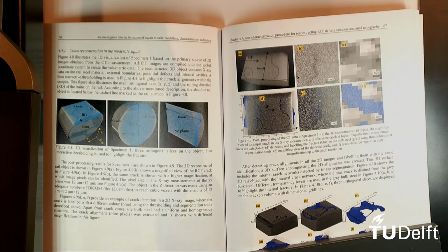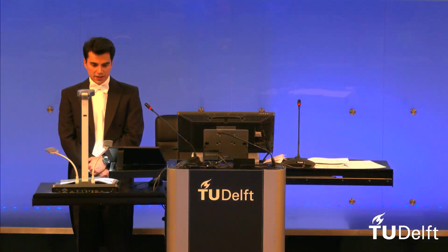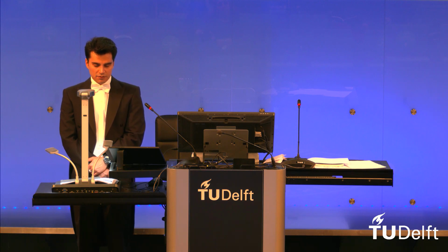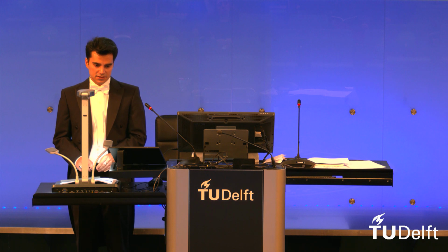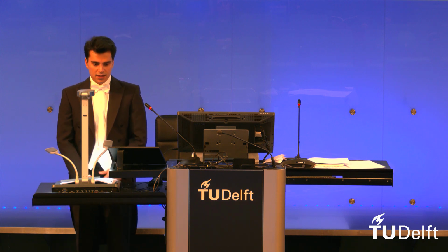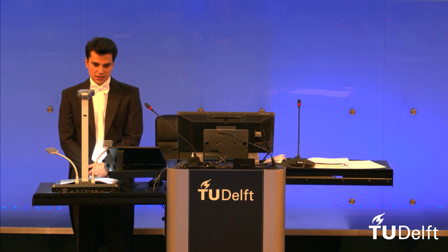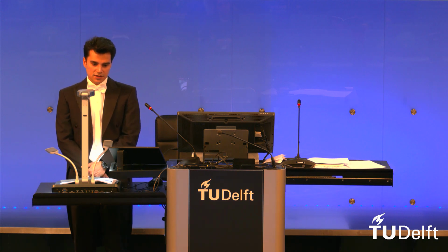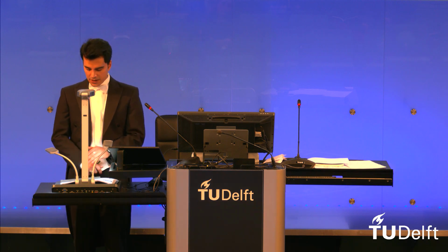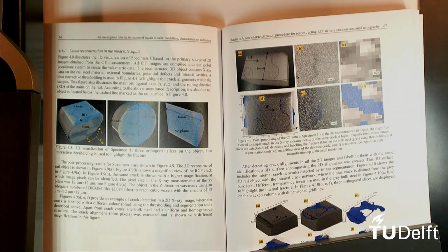And of course, there are also a couple of techniques in the software package which has been developed in order to capture the internal defects, by which you can segment the cracks. It's called the segmentation process. As far as I know, there are 5 segmentation methods which you can apply in order to detect the cracks. I personally do not have, let's say, much background information about them, but I compared them. For example, the results of a gradual segmentation, which is one of the techniques, have been reported mostly in the images. So you apply one by one to see what would be the effectiveness of the method.